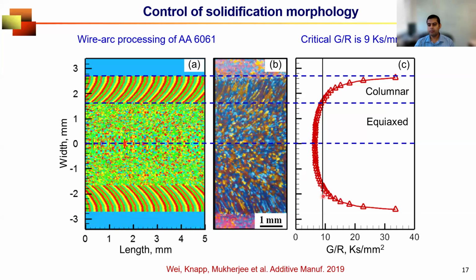Now you see, this is the computed value of G by R. In this region, the value is less than 9, and they should form equiaxed grains, which is proven here from the model as well as from the experiment. Beyond which, the value is more than 9, which means columnar grains. You see long columnar grains being formed, which is also evident from the experiment. So this is a very good example of how you can take advantage of temperature calculation and process it to get useful scientific insight to predict microstructure.